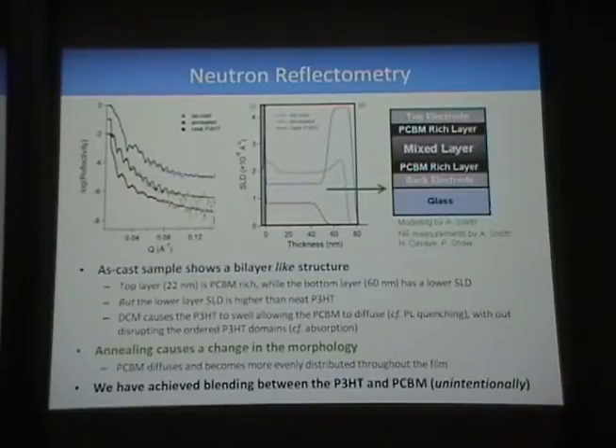So what's happening here is that the DCM is causing the P3HT to swell and allows the PCBM to diffuse into the lower layer. And we saw from the PL quenching that even in the as-cast, you get quite significant quenching. And at the same time, this doesn't disrupt the ordered P3HT domains, as we saw from the absorption spectra. So this is fairly consistent. Now the green trace shows what happens after the annealing step. And you can see that the annealing causes a change in the morphology. The PCBM diffuses and becomes more evenly distributed throughout the film.